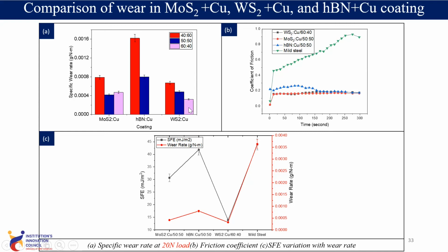Similarly, you can see in the WS2 copper coating, there is minimum wear observed for the WS2 copper coating. This is because this coating also shows low surface energy. So we have established the relation between surface energy and wear rate. It can be shown by this figure that the mild steel surface has larger surface energy, and all the other surfaces are low energy.